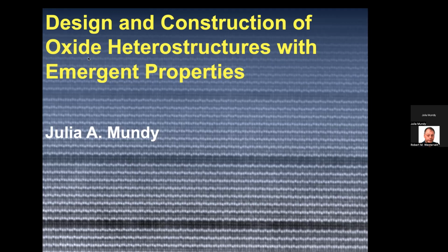And so we're able to engineer such a material that does not exist naturally and to be able to control the functionality. And the really cool thing about this material is that these atoms don't just sit in perfect flat planes. If you see this, you can see that the atoms go up, up, down, up, up, down, up, up, down. And these distortions are picometer distortions. This is about 40 picometer distortion.